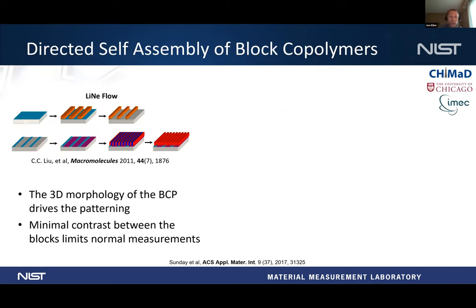And so for the first example here, this is the directed self-assembly of block copolymers, and work that we've done with Professor Paul Nealey's group at University of Chicago. And so this is the process flow that he developed. It's a very similar thing to the spacer-based double patterning that I showed earlier, where you can make a larger pitch pattern and then reduce it in size to a smaller pitch pattern. And so in this particular case, you pattern a chemical template.